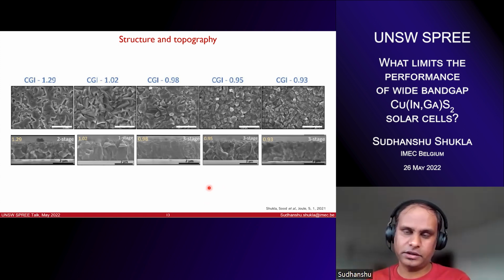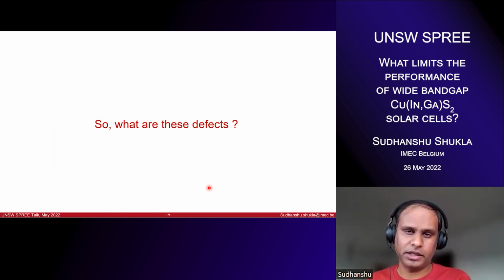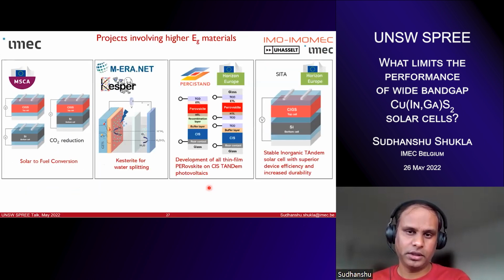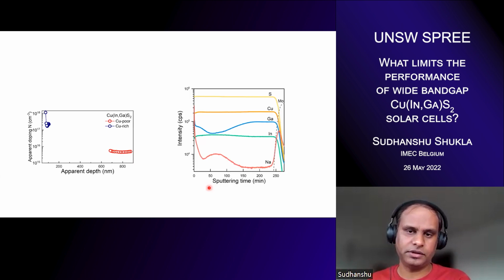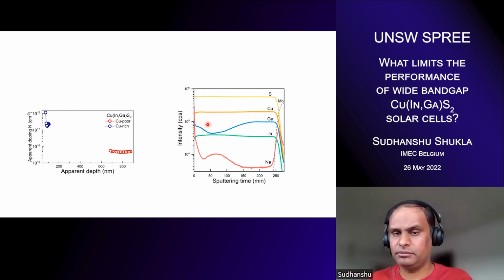And to answer your other question, did we check the accumulation? So I do have something for you, which is here. At the front surface, we do have a high gallium because we are evaporating gallium in the end, which actually helps us. And it also drives the sodium crazy high at the front surface, because when you have a copper-poor surface, the diffusion of sodium is faster. That also might be helping us. We don't know. So these are all the things we need to quantify. We do see a segregation of gallium, not the indium, at the front surface. Actually, that's what we see from our SIMS results.